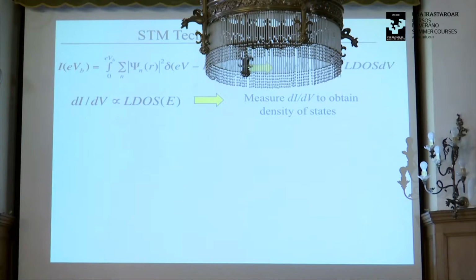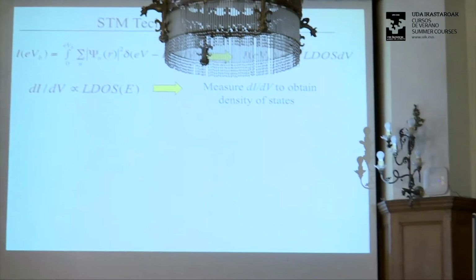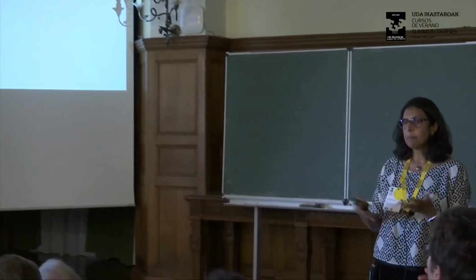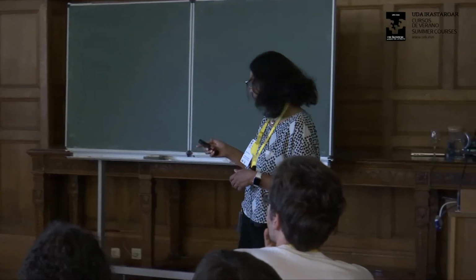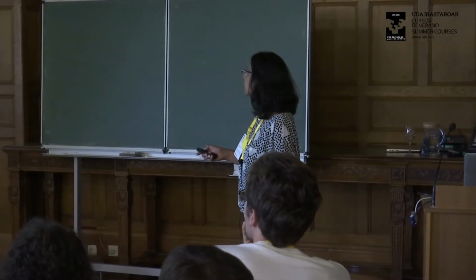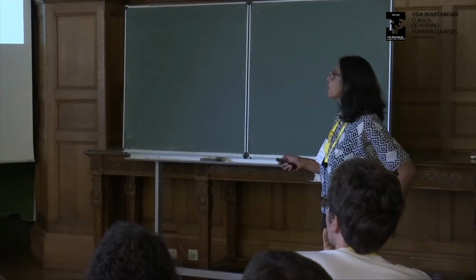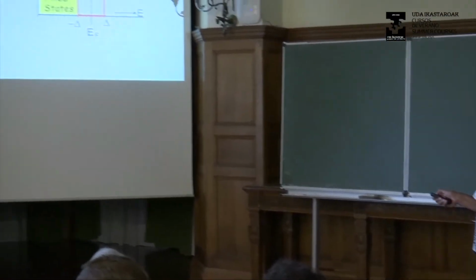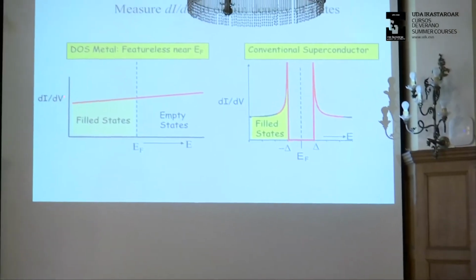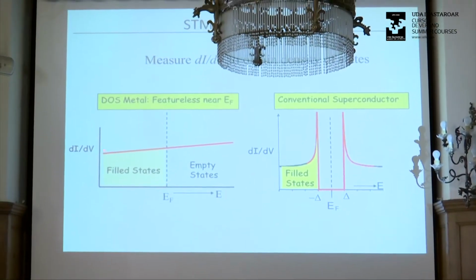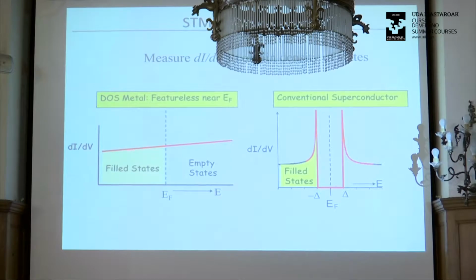So when I show you spectroscopy, I'm going to show you dI/dV as a function of bias voltage. 0 volts is the Fermi energy, and we can measure the density of states as a function of energy using STM simply by measuring dI/dV, right? And so, for example, if you were to measure the dI/dV for a metal, the density of states is featureless across the Fermi energy, so this would be 0. You would just get a flat dI/dV. If you were to measure dI/dV for a superconductor, you would see a superconducting gap with coherence peaks that are symmetric on either side of the Fermi energy.